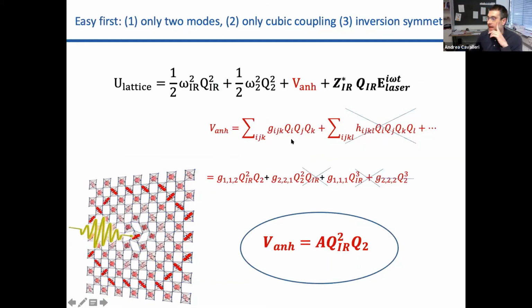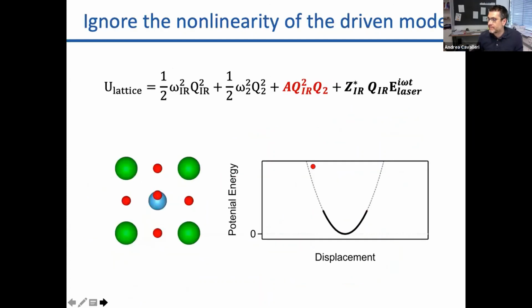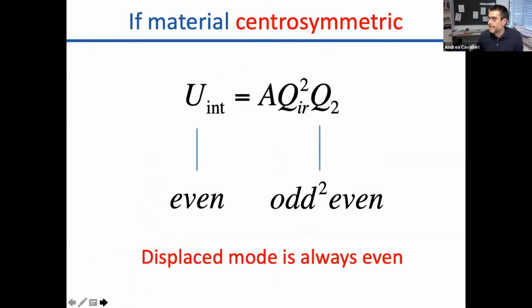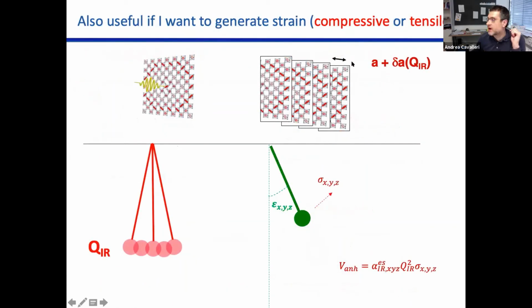Okay, so remember, we restricted ourselves in this anharmonic coupling term to coupling terms of the type Q_IR squared, where Q_IR is the mode I'm driving, times Q2. Now, this Q2 mode can be any mode that is allowed by symmetry. It could be an optical phonon, which preserves volume, which is the more interesting one. But it can also be a strain, say a zone center acoustic phonon that changes the volume of the material. So you should look at coupling terms between Q squared and the stress, which is really an internal pressure, which then gives rise to a motion.